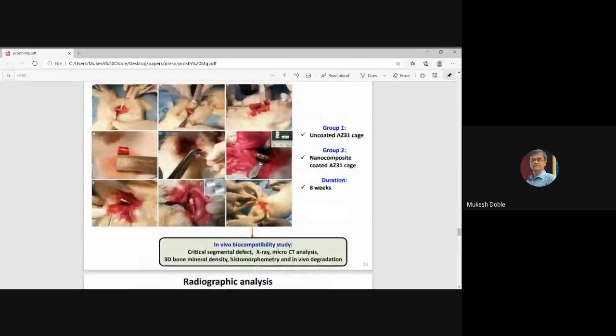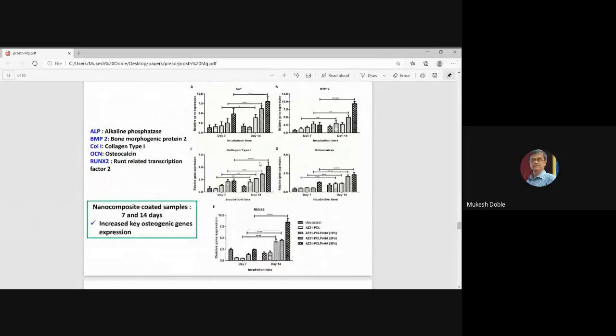We also see the genes which are involved, especially the alkaline phosphatase. We see a similar picture as we saw in our in vitro studies, that the coated surfaces, especially the polycaprolactone and hydroxyapatite coated surfaces, enhance the important genes which are involved in the bone formation as well as in the anti-inflammatory process. So the alkaline phosphatase gene, the bone morphogenic protein gene, the collagen type 1 gene, all these get enhanced in the presence of the coated surface when compared to the uncoated surface. So we see a similar picture as we saw in the in vitro studies.